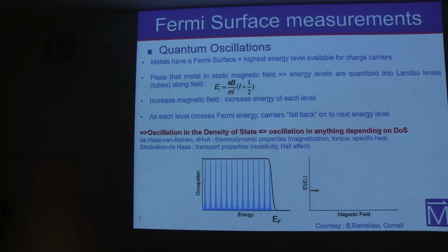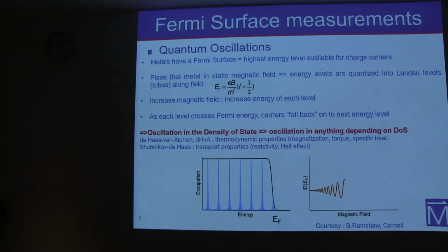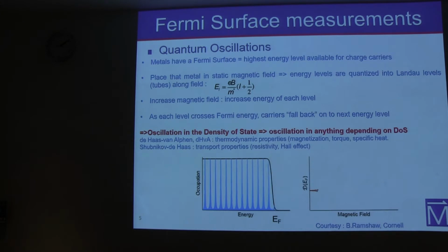Now, any physical quantity that depends on the density of states, as you increase the field, will show oscillations as a function of magnetic field. This is what is shown here. Those oscillations are called either de Haas-van Alphen, dHvA, for thermodynamic properties, so magnetization, torque, or specific heat, or Shubnikov-de Haas for transport properties like resistivity or Hall effect. But those are two different names for the same physical effect, quantum oscillations.